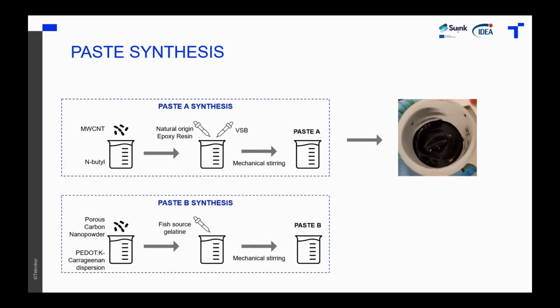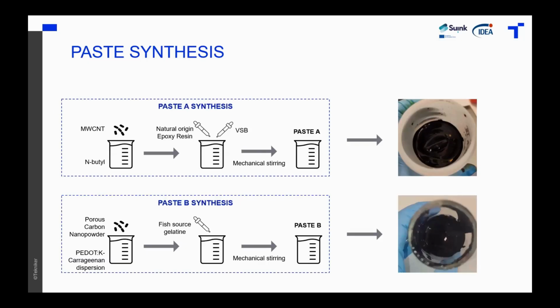The second ink was made by mixing porous carbon nanopowder that, as I have said, is plant-based, with the PEDOT:K-Carrageenan dispersion provided by the POLYMAT, and after dispersing it, we added the fish source gelatin. Also, by mechanical stirring, we get the paste that we could see on the image.